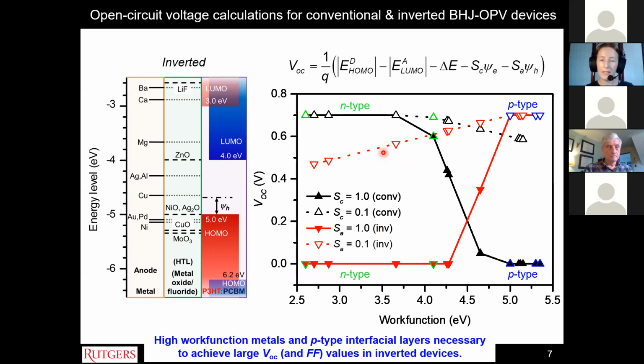And then we did some calculations of open circuit voltage as a function of work function for all of the various materials that we were interested in using. And you can see that for a conventional device, as you increase the work function, the open circuit voltage drops significantly once you start using a high work function metal as the cathode in this case. And that makes sense because you're going to create a large barrier for electron collection.